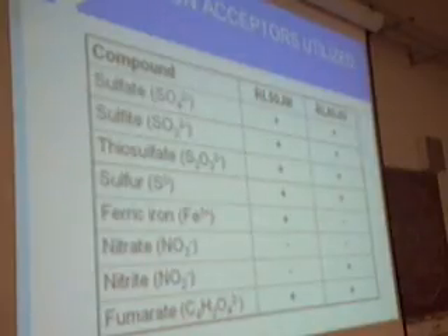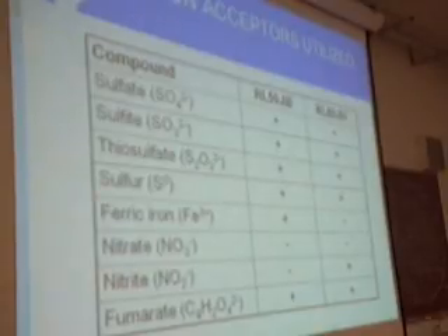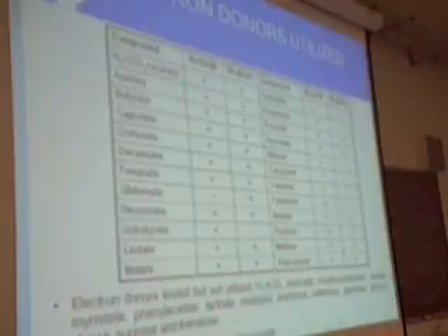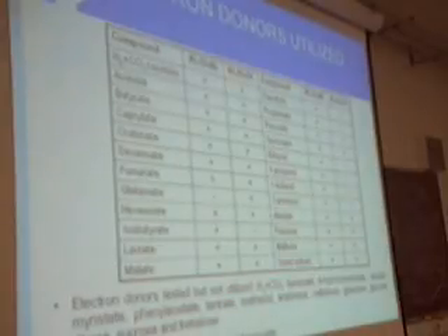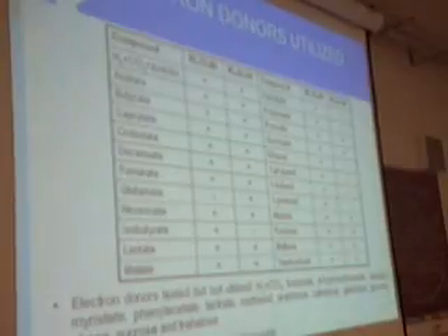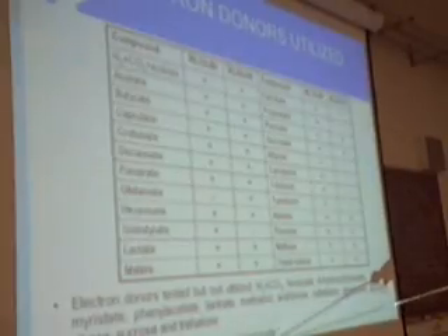Then the strains could use quite many different electron acceptors, which are shown here. So in addition to sulfate, they could use sulfite, thiosulfate, and sulfur, as well as fumarate, and then this strain could also use ferric iron, and this one nitrite. And there were also many different electron donors that they could use. Most of them are common fermentation products or degradation products of larger organic polymers. And if there were no electron acceptors present, the strains could also ferment lactate and pyruvate.